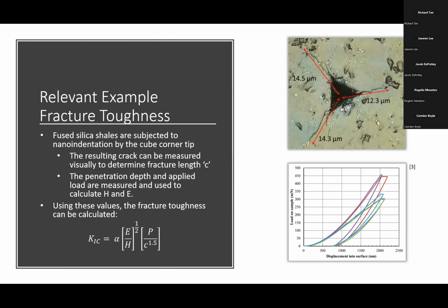Getting into some relevant examples, the first is measuring the fracture toughness of a brittle material—in this case, a fused silica glass subjected to nano indentation by a cube corner tip. You can see the picture in the top right: it was indented with the cube corner tip, and there was a radial fracture from each corner.